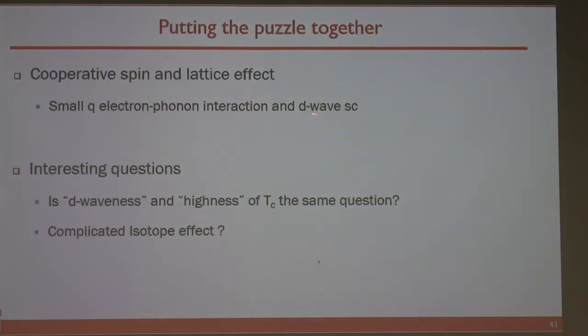So if I now put this together, then we can say that there's a strong spin interaction and there's also a lattice effect. But usually, electron phonon is bad for a d-wave superconductor, right? Because it is pair breaking. Unless you have a situation where the momentum transfer is small. Okay. And it's actually on the forward scattering of that. So these two could happen.